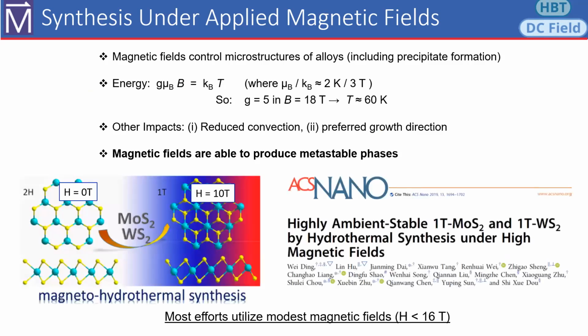And indeed, this sort of work has been happening. This is from a group in China where they've been doing magnetohydrothermal synthesis of these dichalcogenides. And sure enough, in a field of 0 Tesla, you get one structure. In a field of 10 Tesla, it fully converts to the other structure. So this is totally wide open. It's almost like you can read all of the literature in this field. So much work to be done here, and I think the message is stay tuned.